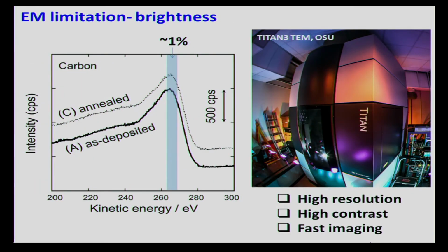But a critical limitation that sort of narrows the application of this technique is the brightness. And the reason is that when we take a diamond or take a field emission material and generate electrons out of it, what you have is really sort of a messy or dirty bunch of electrons. They have all kinds of different angles when they go out of the surface. They have different kinds of energies as well. And to do really high resolution imaging, what people do is they sort of slice this really broad range of electrons and just take a very thin piece of it.